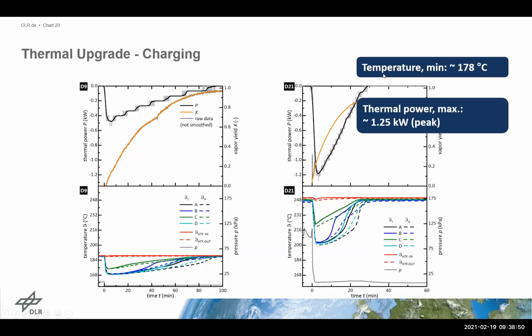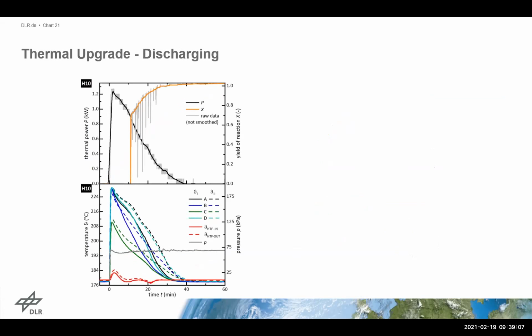So just to summarize all of our experiments there, we have, of course, the possibility to play with temperatures. The minimum temperature we have used was something like 180 degrees Celsius, and the maximum thermal power was 1.2 kilowatt peak. For the discharging, same thing. We said, okay, let's keep the temperature constant. It's the same temperature, so there's no charging and discharging loss of the quality of the thermal energy. It's the same quality of the thermal energy after discharging. And in this case, of course, it's the best case for our system.